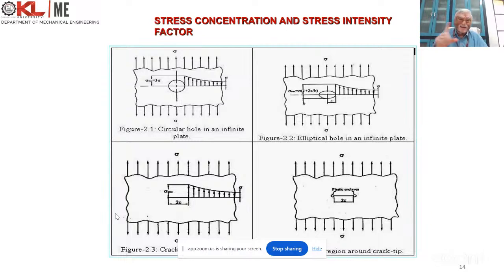When we introduce a cutout like a circular hole in a simple tensile specimen, if the circular hole is not there, you can expect uniform stress distribution. The moment a circular hole is there, whatever load you have applied for a wide plate, 3 times that stress will come near the vicinity of the hole. If it is an elliptical hole, again, at the small radius of curvature, the stress will be high. If the elliptical hole's minor axis is reduced to 0, it becomes a crack, so the stress concentration will become infinity. So it would be unable to take any load for infinite stress concentration, whereas in the presence of a crack, it is able to take the load. That way, the strength of material fails to give the correct factor of safety in the presence of crack-like defects.